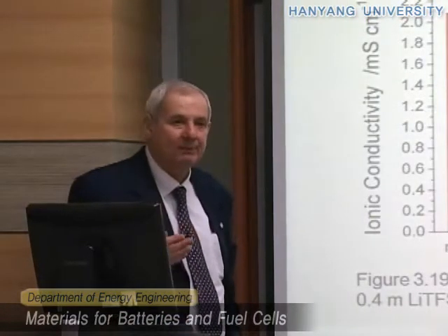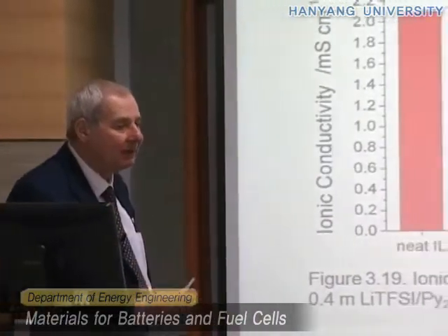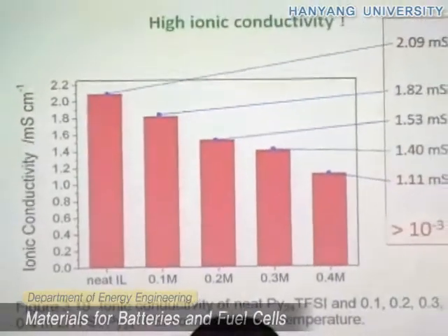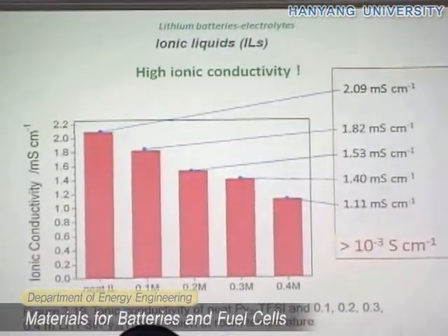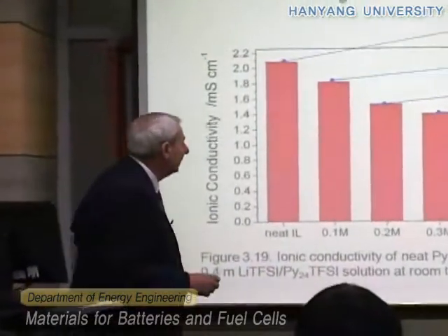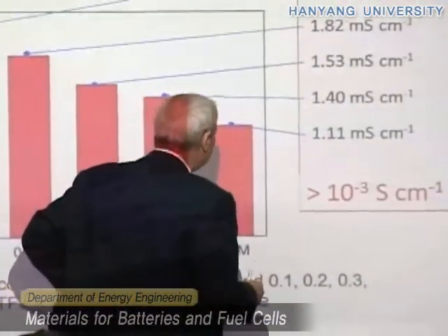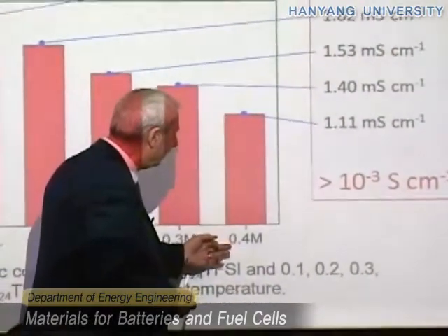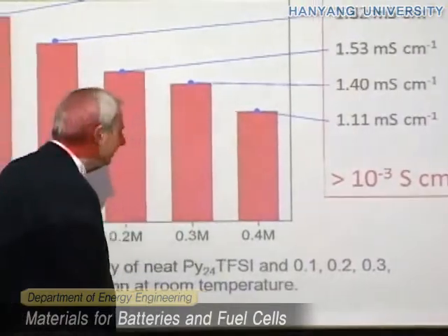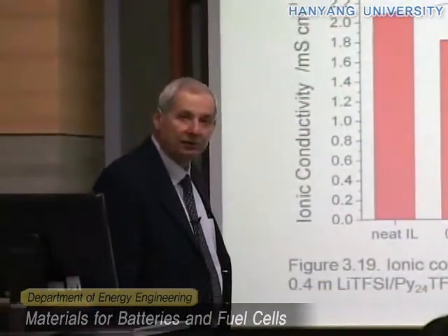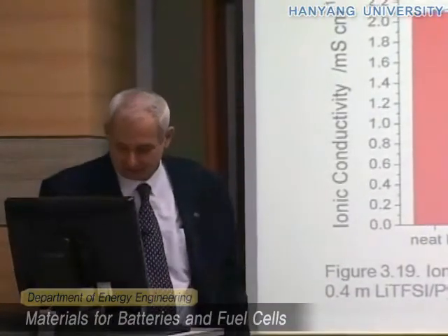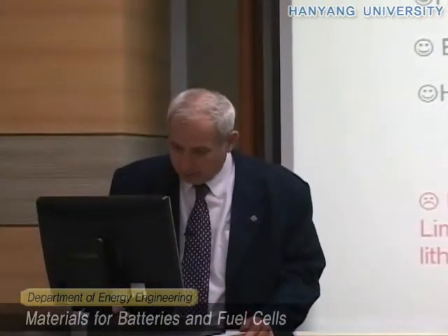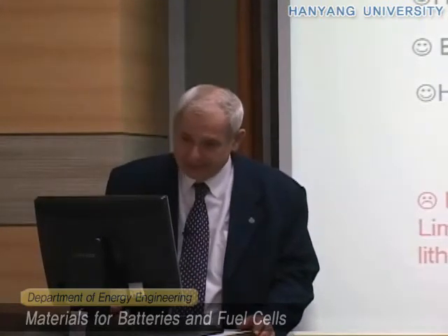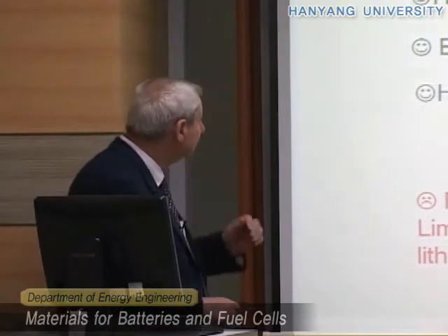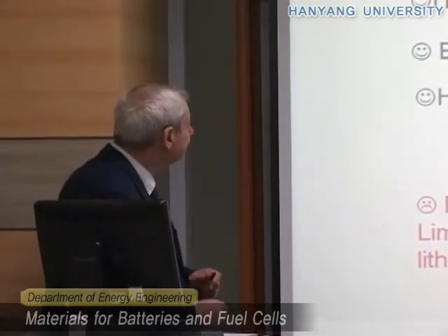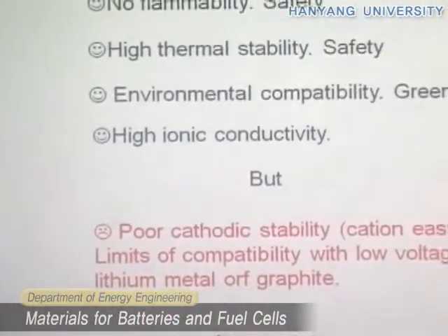And of course, when we add some lithium salt into the ionic liquid, the conductivity decreases because we increase the viscosity. But still, even at a reasonably high concentration, 0.4 molar, the conductivity remains higher than a millisiemens, so conductivity is not really a problem because it's more or less the same value as the standard electrolyte. So there are some very promising features here. They make these ionic liquids very promising electrolytes for batteries.